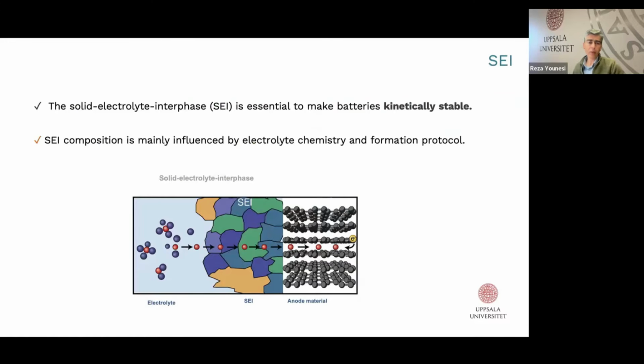A very brief information about SEI, or solid electrolyte interphase. It is a very thin layer, a few nanometers, made of inorganic and organic species, crystalline and amorphous components, and it is very essential to make batteries kinetically stable. Because, as you know, the electrochemical potential of most anodes like graphite or hard carbon is below the electrochemical stability window of electrolytes, which means that batteries are not thermodynamically stable.